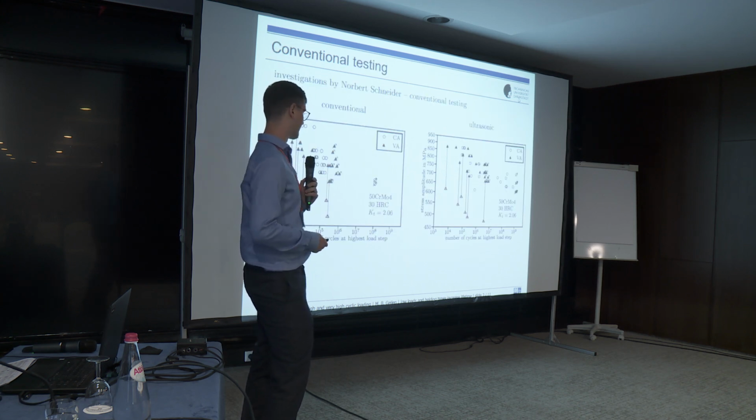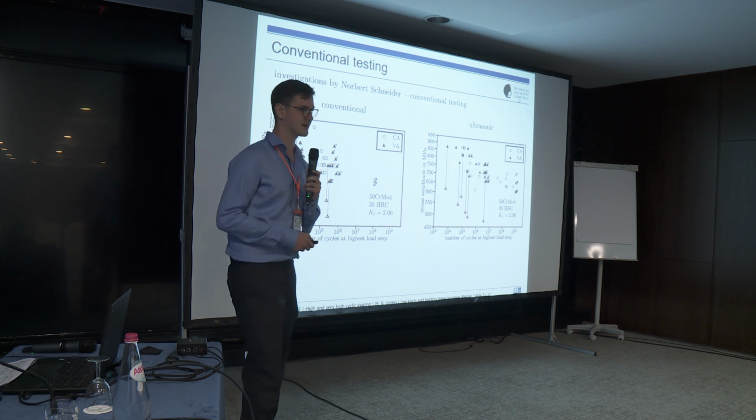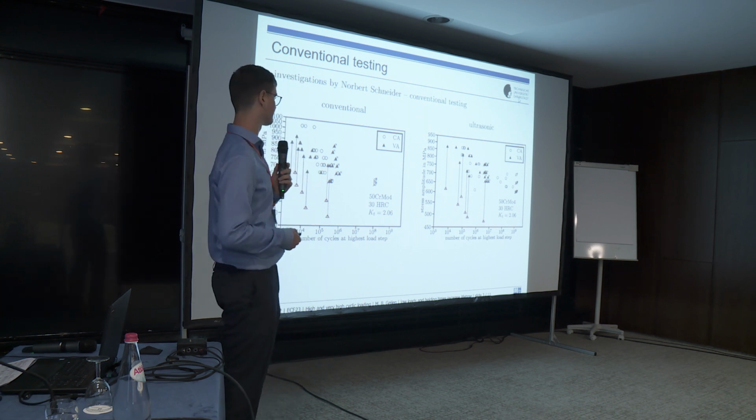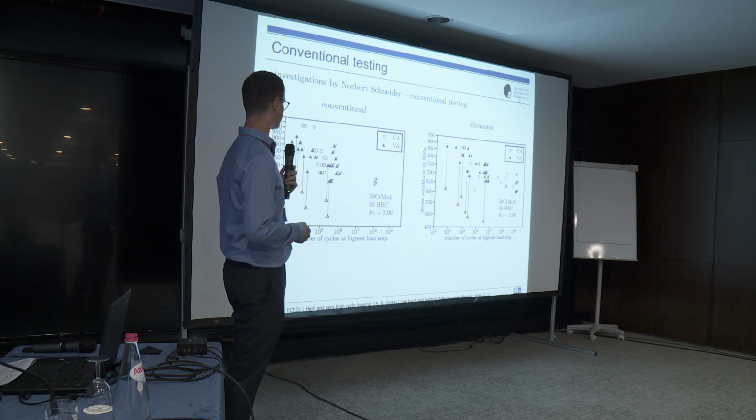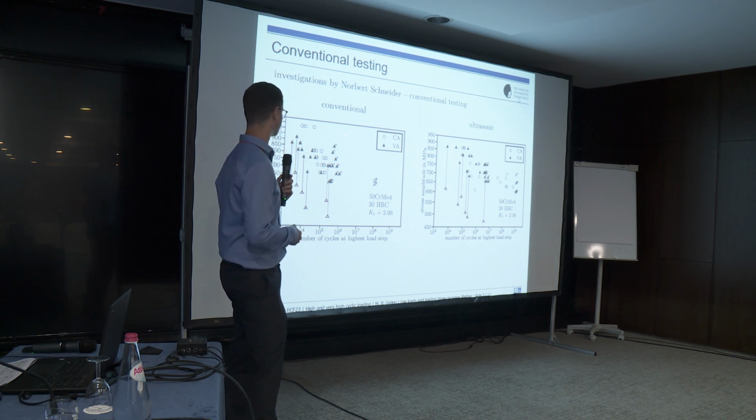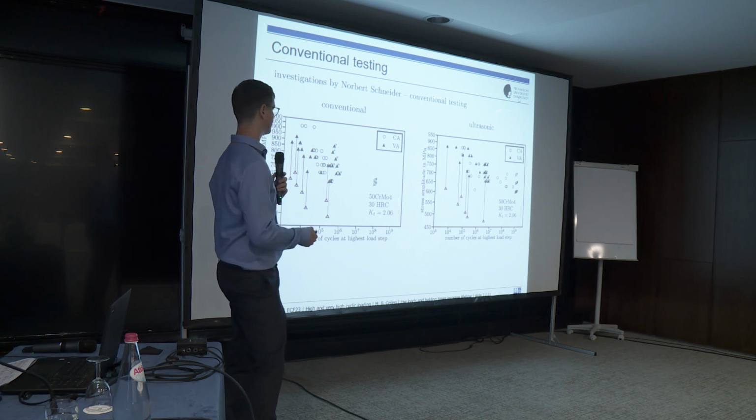This was done in ultrasonic testing, and one may argue that that's an artifact of ultrasonic testing, but that argument is false because our Norbert Schneider did experiments in conventional and in ultrasonic testing, and here we also see in the same diagram the increase of lifetime due to low amplitudes.